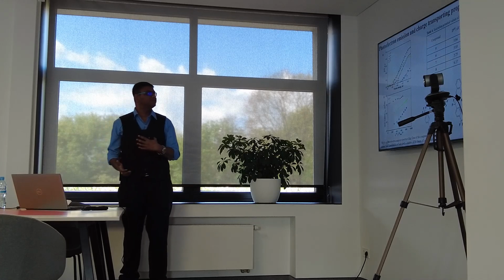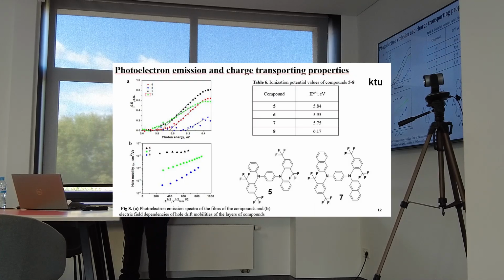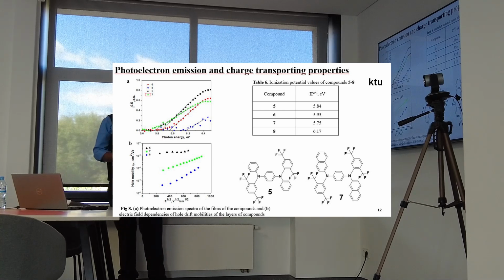with naphthalene units. The photoelectron emission and charge transporting properties of the materials were studied, and it is revealed that for compounds 5 to 8 the ionization potentials are in the range of 5.7 to 6.2 electron volts, and the time of flight measurements revealed that the hole mobilities for compounds 5 and 7 are 10 power minus 3 and 10 power minus 4 square centimeters per volt seconds.